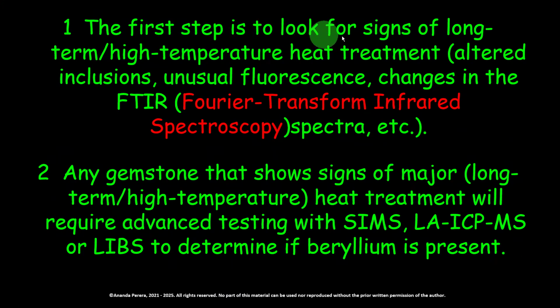One, the first step is to look for signs of long-term high temperature heat treatment. That means altered inclusions, unusual fluorescence, changes in FTIR, which is the test. FTIR is Fourier transform infrared spectroscopy. With FTIR we can find if it is heated or not. Any gemstone that shows signs of major long-term high temperature heat treatment will require advanced testing with SIMS or LA-ICP-MS, very advanced technology, or LIBS, to determine if beryllium is present. FTIR is for heat treatment. If it is heavily heated, SIMS, LA-ICP-MS, or LIBS determine if beryllium is present. These are the tests you should understand.